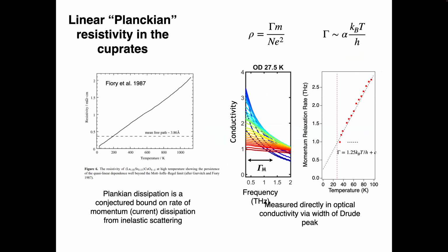So this is data that I started with yesterday. We might want to know something about this, why we have this behavior here. This is the resistivity versus temperature for early data on lanthanum strontium copper oxide. And as I pointed out, this is linear in T behavior all the way up to something of order the melting temperature for lanthanum strontium copper oxide. This sample is red hot by the time it's 1,000 Kelvin, and it's still the same linear law that takes you all the way from 40 Kelvin all the way up. So this is kind of remarkable, and it's something we still don't understand.